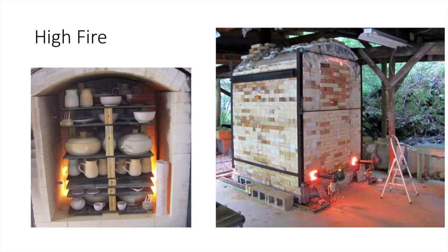not as exciting. And so the way that you reduce the oxygen and increase the gas is you can turn the blowers off when you're letting the gas into the kiln on the burners. Usually there's a damper on the top of the kiln. Sometimes there's one on the bottom. And you can close off the damper to allow less oxygen to escape and kind of choke out the kiln that way.